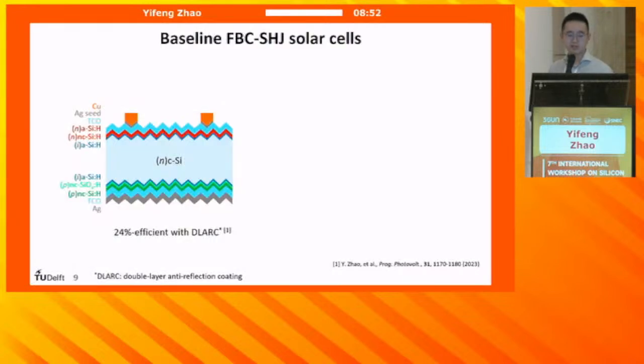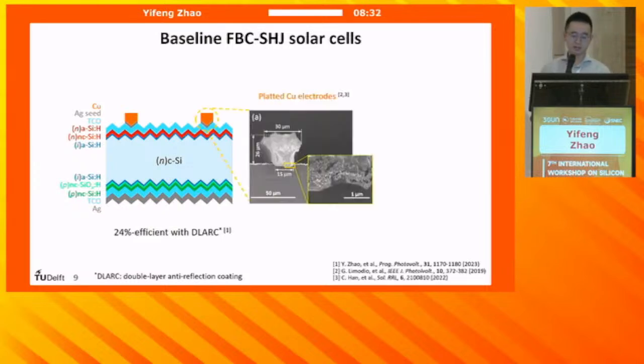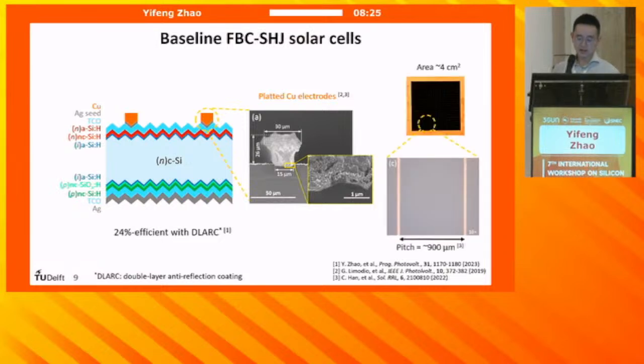So first, let's start with the baseline heterojunction solar cells we have in our group, which is around 24% efficient, that features nanocrystalline silicon-based P-type layer on the rear side, and a bilayer N-layer stack consisting of N-type amorphous silicon and N-type nanocrystalline silicon layer on top, and finished with copper-plated electrodes. So let's have a closer look at our copper-plated electrodes, which have high aspect ratio and are also conformally plated on the surface. And if we look at the solar cell that we made, thanks to the plated narrow copper electrodes of around only 15 micrometer wide, we have a metal coverage of 1.5%, and also a pitch size that is around 900 micrometer, and this is close to our optimum pitch value according to the simulation.